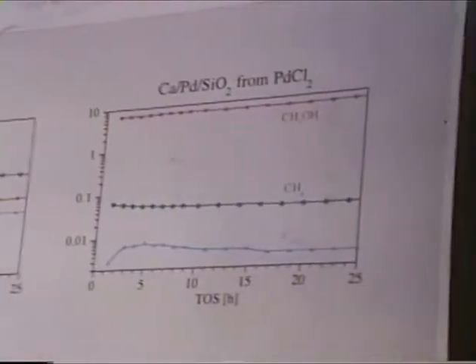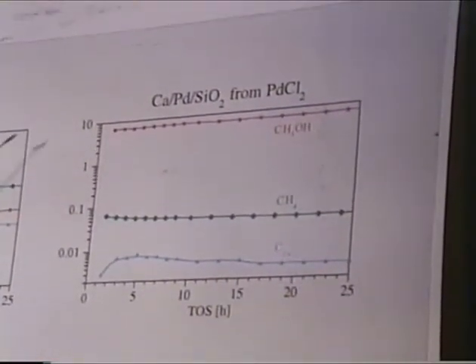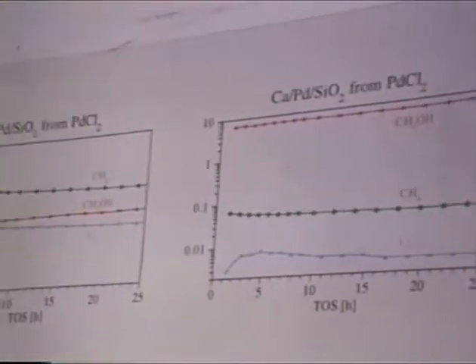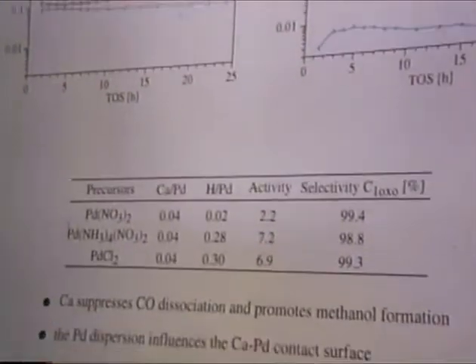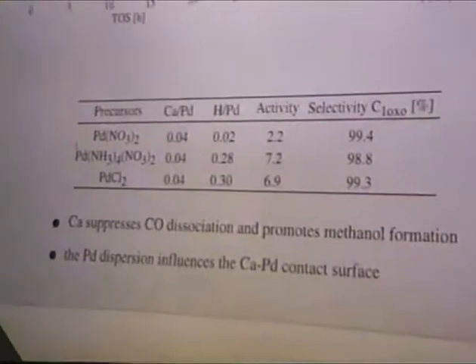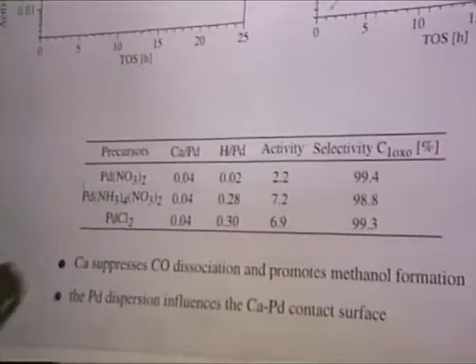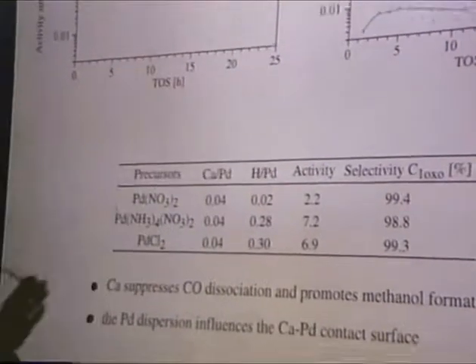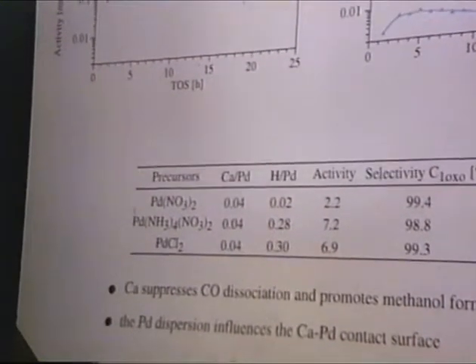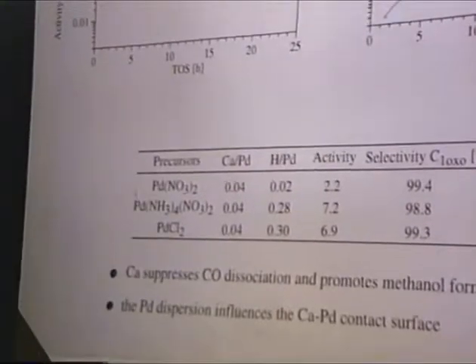Now then it was obvious that it must have to do with something like an impurity. So one of the best in our hands was calcium, and here you immediately see what happens. You take a palladium on a very pure silica. The impurity level is down to the ppb level. We checked it with ICP. When you dope it with calcium, and this is something like 1000 ppm, which is like 0.05 calcium versus palladium, I'll come back to it. You see that the methanol shoots up almost 2 orders of magnitude, and the methane and the C2+ are suppressed.